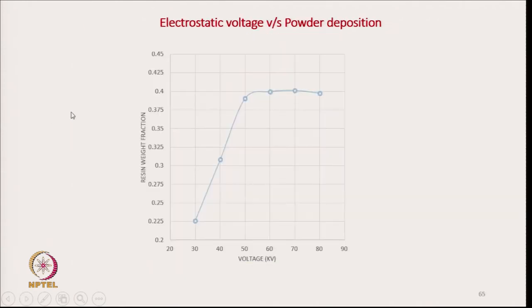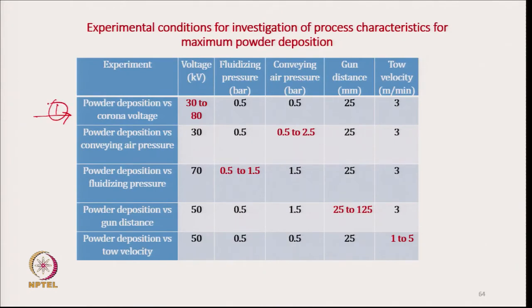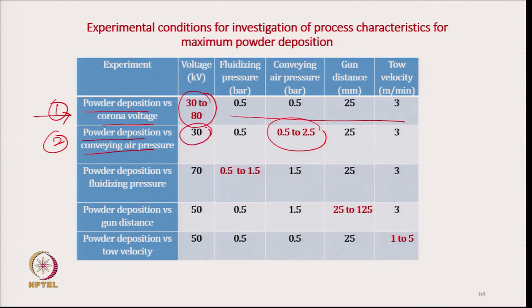In the first experiment, powder deposition versus corona voltage. Corona charge was varied from 30 to 80 kilovolt, and the rest of the parameters like fluidizing pressure, conveying air pressure, gun distance and tow velocity were kept constant. Similarly, in the second experiment, powder deposition versus conveying air pressure. Conveying air pressure was changed from 0.5 to 2.5 bar, where the corona voltage was kept at 30 kilovolt, and other parameters were kept constant.